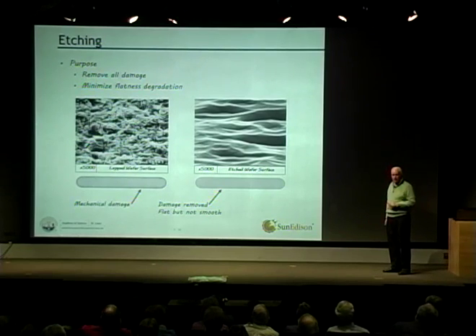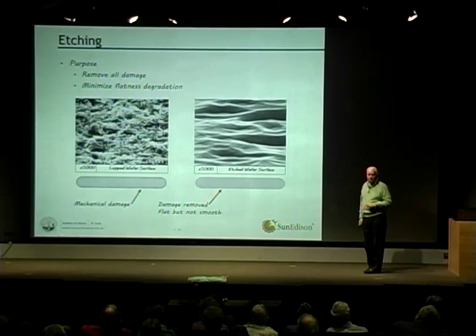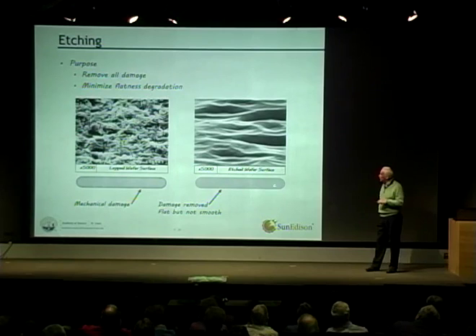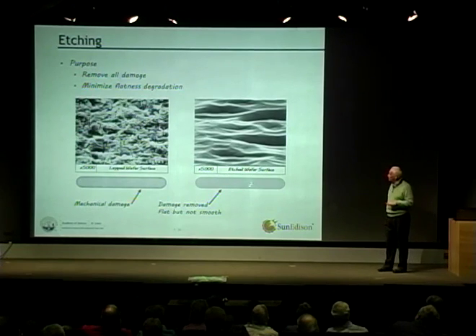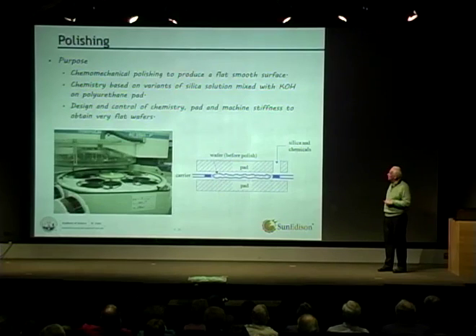And then what we do is we take that and we chemically etch it. Now, remember, when it comes off here, it's as flat as it's going to get. So when we etch it, we need to make sure that we don't degrade the flatness. And when we etch something chemically, it removes the damage and leaves a damage-free surface and a stress-free surface. We then take that surface and we polish it.